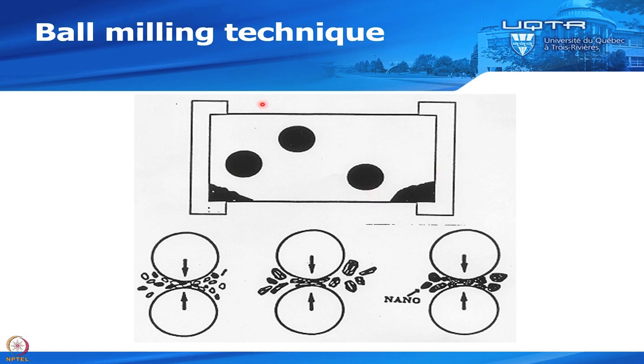And of course, if you have powder in your crucible, then you will have powder that is trapped between two balls, or between a ball and a wall. So when the two balls collide, the powder that is here will be broken. Or there could be a cold weld. The two particles could be cold welded together with the force of the impact of the two balls.